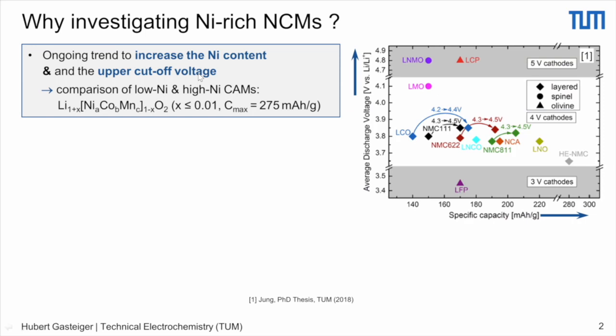And then in recent years also, there has been attempts to gradually increase the upper cutoff voltage. So it is of course interesting to see what the degradation phenomena of these different materials are at high nickel contents and at high cathode potential. So the materials we talk about are these layered transition metal oxides with a very small excess of lithium and a theoretical capacity of 275 milliamp hours per gram if you were to extract all of the lithium.